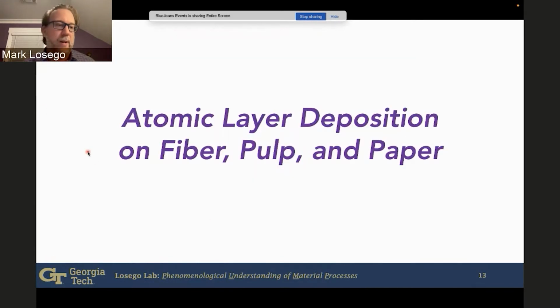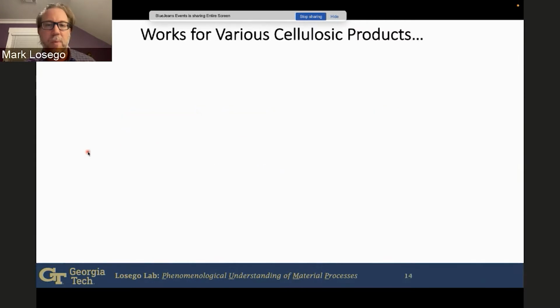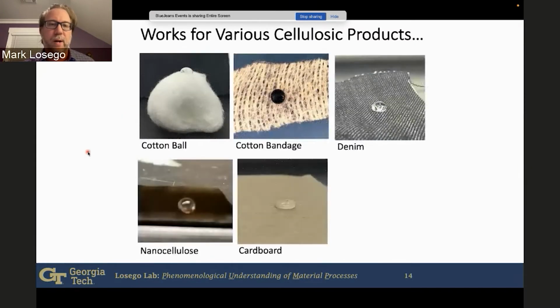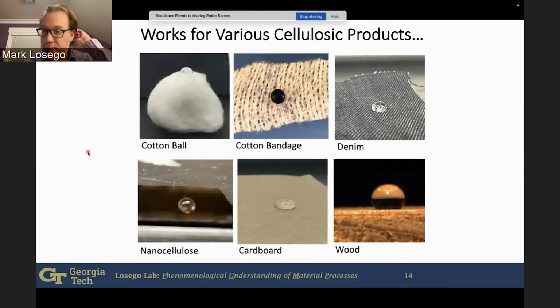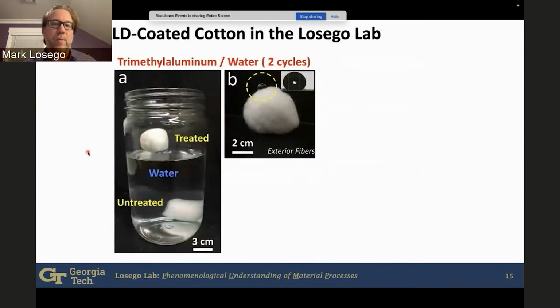So to wrap up, a little bit about atomic layer deposition on fiber, pulp, and paper. We can do ALD on a number of cellulosic products. Examples here: cotton balls, bandages, denim, nanocellulose, cardboard, and wood. And what we find is that when we coat these, they become hydrophobic. They repel water. They actually float on water.